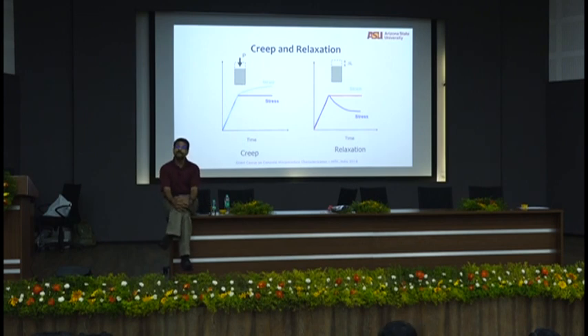But what happens with a very high-strength concrete with respect to elastic modulus? Elastic modulus is a function of the square root of the strength, right? So what happens when the strength goes up? Elastic modulus goes up. What happens when the elastic modulus goes up? Think simple linear elasticity. Stress is elastic modulus times strain. For the same strain, what happens when elastic modulus goes up? Stress goes up. What happens when stress goes up? You are likely to have microcracking.